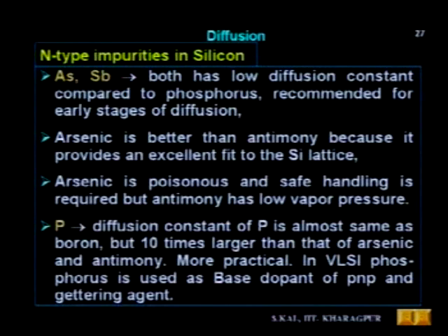Okay, low vapor pressure is not always desirable. These are the comparison of the properties as a dopant between arsenic and antimony. Now if you look into phosphorus, we have found that the phosphorus diffusion constant is the same as boron, but the diffusion constant of phosphorus is 10 times larger than that of arsenic and antimony. That means it is a faster diffusion compared to arsenic and antimony.